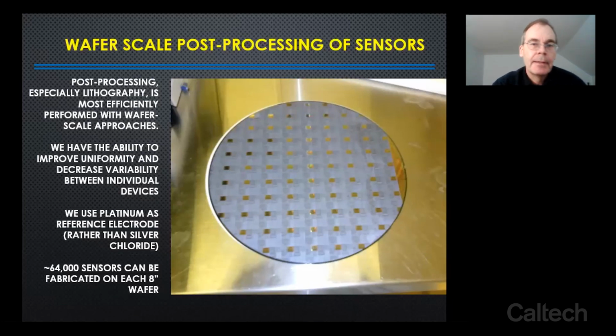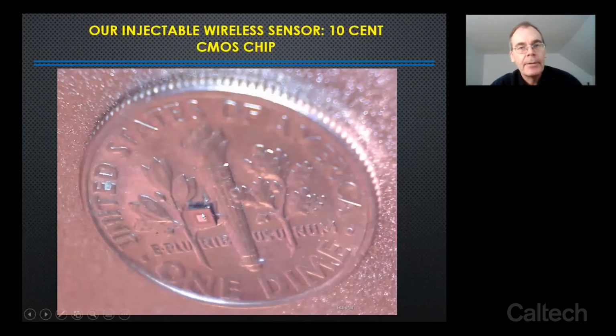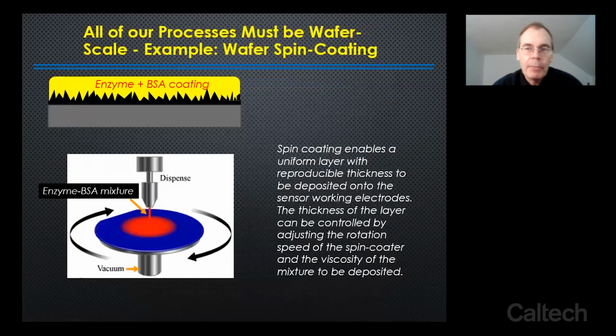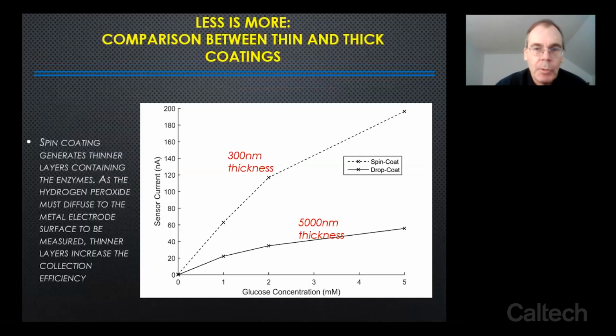So that's why I have this device on a 10-cent dime, okay? The idea is that everything we do in order to get there, though, has to be wafer process compatible. So instead of using more common enzyme deposition techniques, we have to use essentially spin coating. Now, spin coating gives you very thin layers, very uniform layers, and we spin coat our enzymes. It took us a while to figure out how to do it, but it turns out it's a very effective way, and surprisingly, when you make these layers by spin coating, you can make them much thinner than what you normally would have. And for me, it was surprising that these thin layers are much more efficient.